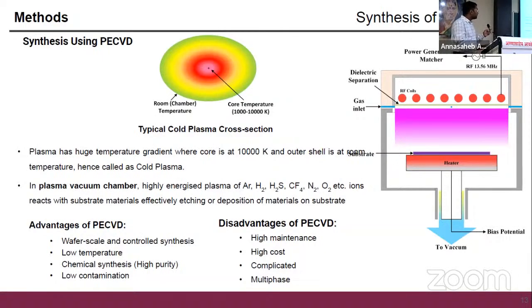So typically, if you see the plasma CVD chamber, there is some heater in order to heat your substrate. So we can heat up to our desired temperature. The heat requirement is there because the plasma can also move depending on the temperature as well as the electric field, since it has ionic nature. So depending on heat also the plasma can move, so we can control the adsorption of plasma on your substrate. So that's why the heating requirement is there.